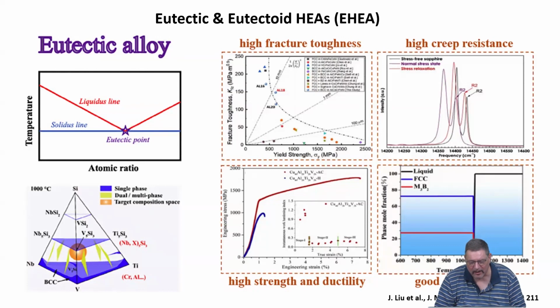And also there you have many beneficial properties, especially in terms of the mechanical properties, so high strength and good ductility, because of many phase boundaries which you are having in the material. So here you would not have a transformation-induced plasticity, but you have a dual phase eutectic microstructure. Which microstructures do you know in eutectic systems to form? Yes, you can have rod-like, you can have lamellar, you can also have dendritic, and all of this is basically